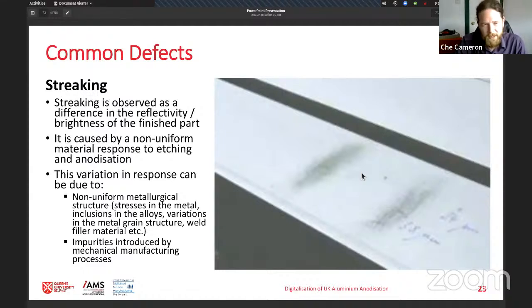Streaking is basically a slightly dull looking section, or basically a different looking section in the anodized finish, which should be uniform. And the problem with that is the metal hasn't responded the same way as the rest of the piece to the anodization process. So the film hasn't grown in the same way. And this arises because of maybe stresses in the metal or inclusions in the alloy, or any little impurities that have been introduced or ground into the metal structure. And again, a lot of this can only really be prevented by carefully handling the material and being thoughtful with the manufacturing, bearing in mind the final finish that you want to put on the part.